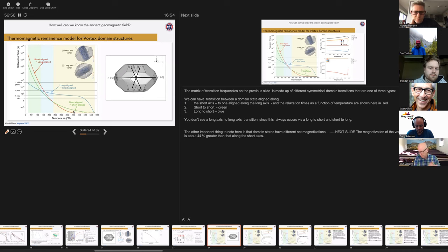So the grain, these Arai plots are for a monodispersion. So they are 100 nanometers. We always like to quote things in terms of ESVDs, which is the equivalent spherical volume diameter. Anyway, it's a hundred nanometers. Thirty percent elongated along the one zero zero axes. And, it was chosen because it was just on the boundary. As you emerge from this unstable zone that we predict from our 2017 paper, we chose it because we didn't know actually how it is going to behave thermomagnetically. And we wanted to look for something that was likely to have a large effect. In the end, it has a very large effect, much more than we probably would have liked. But the principle here is that we have a grain that has different domain states of similar energies in it. I think that's the principle.